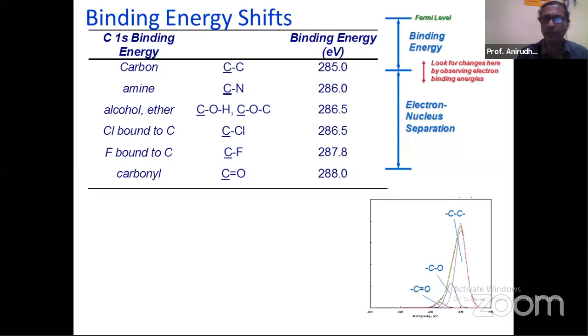So you can use this equipment to identify elements. You can identify their bonding with some prior information about the different kinds of elements that you would expect at the interface. That is important: you have to reduce the number of elements you are expecting at the interface. For example, if you are doing an experiment using steel with a hydrocarbon oil, obviously you won't expect the presence of, say, uranium there. You would expect iron, carbon, some amount of silicon, and something else also. If there is an additive, say lead in your lubricant, you may expect lead also. So that set is finite, it's very small.